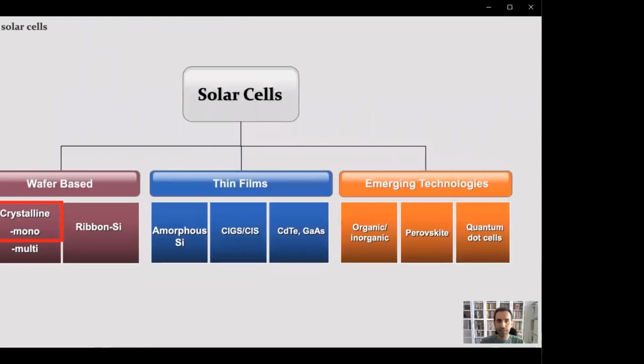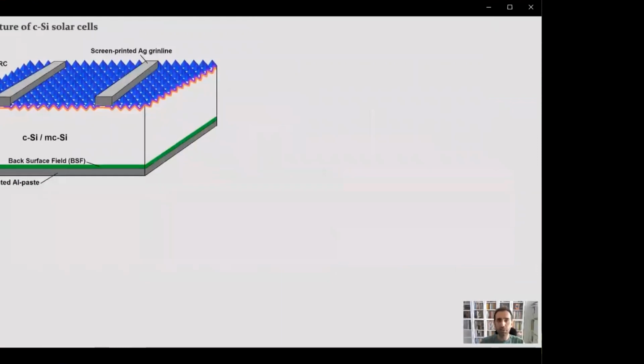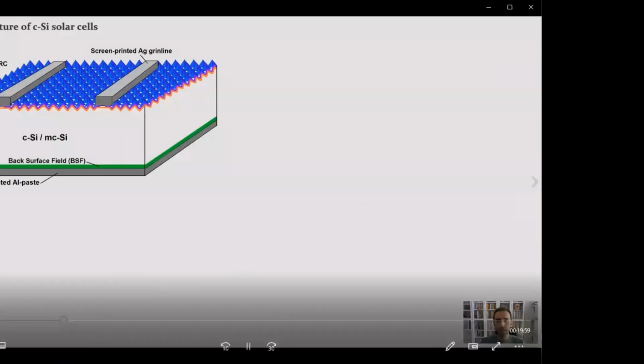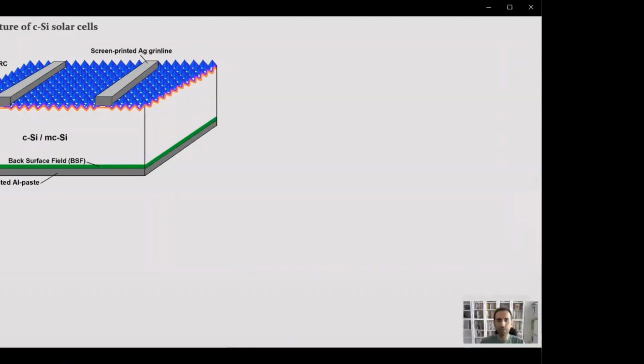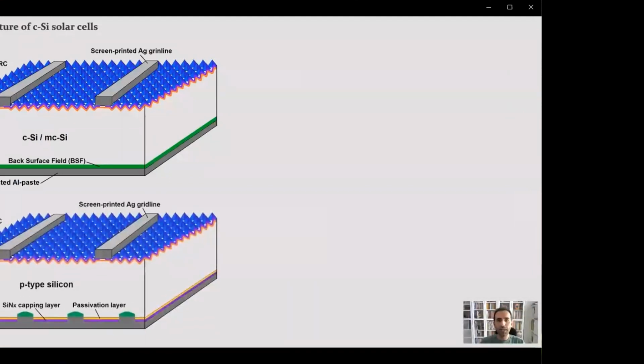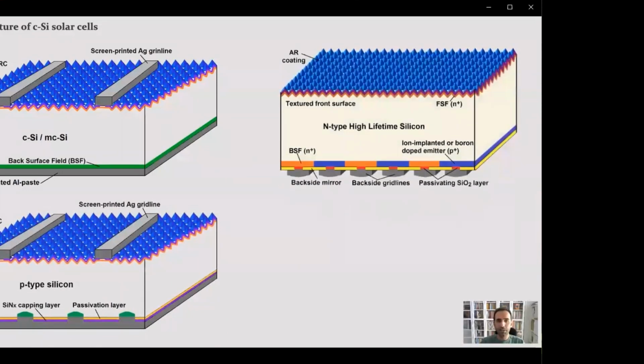In crystalline solar cells, there are also different architectures to better the performance. The first one is the aluminum back surface field structure that has a full aluminum back contact. It has passivation on the front surface and back surface field formation on the back side because aluminum alloys with silicon during high temperatures. This structure is the most common one in the industry because of its simplicity. The second one is the passivated emitter rear cell, or PERC, structure that is very similar to the aluminum BSF, except the fact that there is a passivation stack layer on the back side and the back contact is local instead of full.